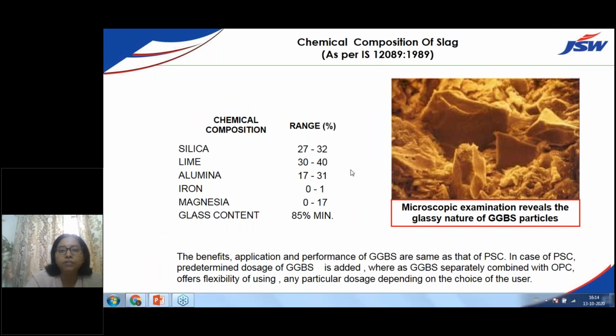So what is the chemical composition of GGBS? I would like to tell you. You can see the unique composition which makes GGBS have a high percentage of calcium oxide. Any other product, you will not see this. If you compare fly ash to GGBS, you can see the calcium oxide content goes beyond 30 and up to 40%. The glass content is also 97.5%. It is very, very fine glass content.